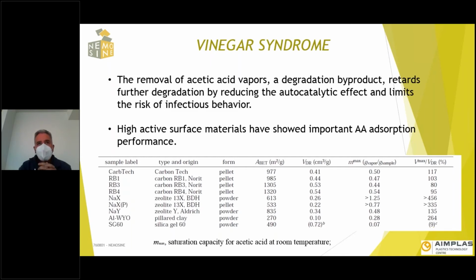The MOFs, the metal organic frameworks, offer, compared, for example, with the zeolites, a better selectivity for specific gases, in this case acetic acid. The zeolites, in another way, offer more thermal and chemical stability, but that is not the case for this application. In this application, we are not working at extreme conditions. On the contrary, we need to control a lot of the environmental conditions. And in this case, the zeolites do not have this advantage. The MOF and the selectivity and the performance as gas sorbents is very important in this kind of application.